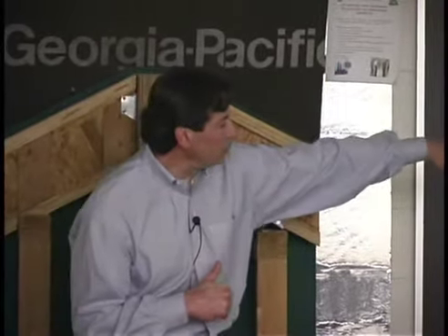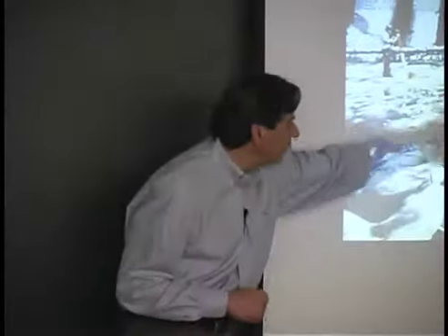And this is the result of, they lost a foot of concrete that abraded away, and they actually were in danger of losing their whole stilling basin. So they put 13,000 PSI concrete on here as abrasion erosion resistance, and that was done in 83, and we're now up to 23 years.